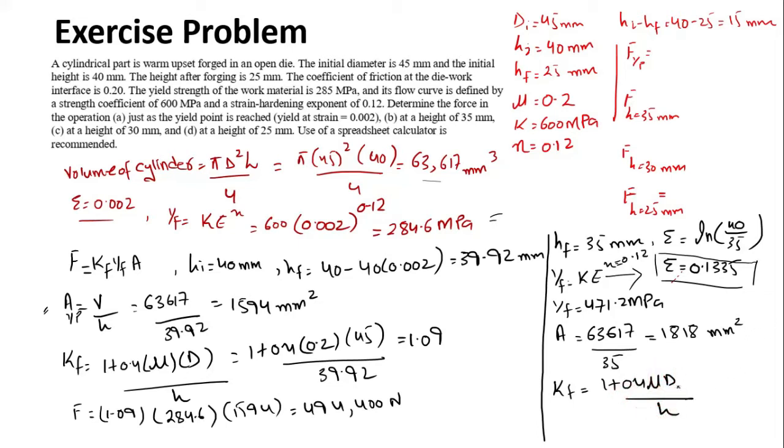Now our diameter has also changed because we have a change in area. Last time we neglected the diameter change because it was really small, but in this case, as we have a larger change in the height and cross-sectional area, it means we have a greater change in the diameter as well, and we have to identify that. We know the value of h, that is equal to 35.